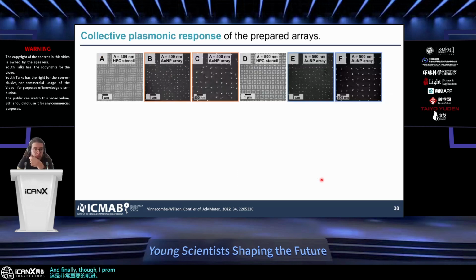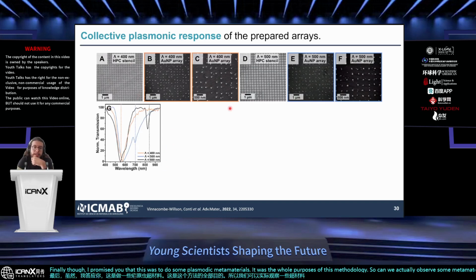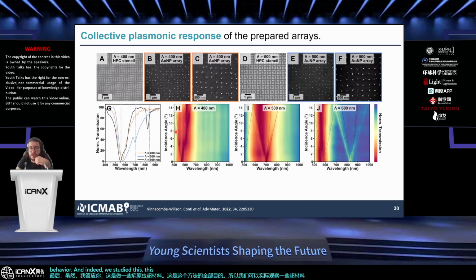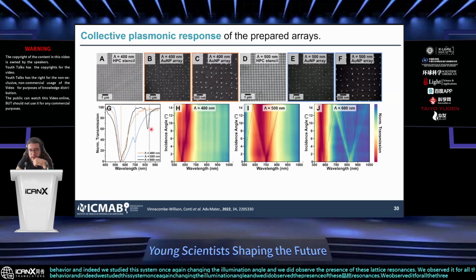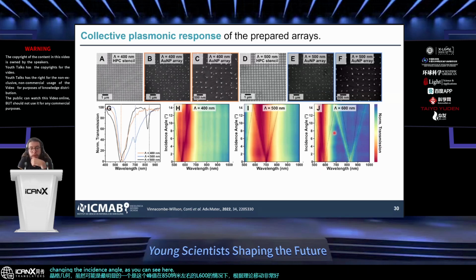Finally, though, I promised you that this was to do some plasmonic metamaterials. It was the whole purpose of this methodology. So, can we actually observe some metamaterial behavior? And indeed, we studied this system, once again changing the illumination angle, and we did observe the presence of these lattice resonances. We observe it for all the 3 lattice geometries, although probably the most evident one is this peak here around 850 nanometers for the L600 case, which moves very well according to theory when changing the incidence angle, as you can see here in this contour plot on the right.